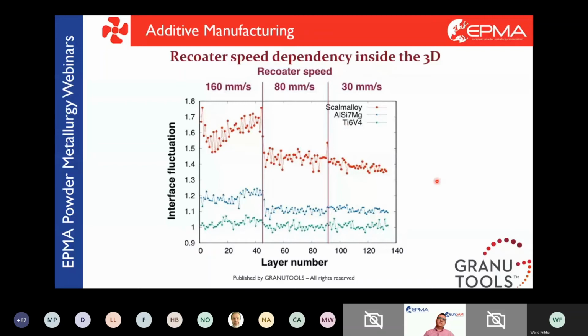But this interface fluctuation system is very complicated because you need to fill the printer with powder, recoat the powder, take a picture, and then measure the interface fluctuation. So the question is, if we do the test inside the rotating drum, which takes less than 15 minutes and only requires 50 milliliters of powder, will I get the same sorting?